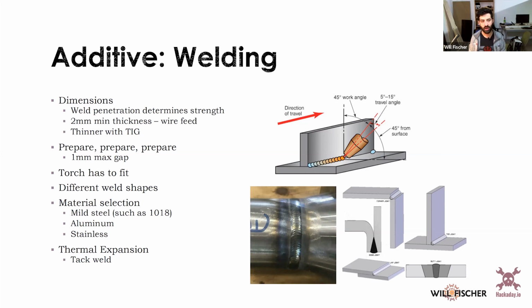Weld penetration is an important part of your structural capacity. If you have two pieces of 6 millimeter thick steel, and you're trying to join them together, but your weld only goes 2 millimeters in, your part will always fail at the weakest point. So you're going to fail along that weld because you didn't get your weld penetration deep enough. Most conventional wire feed welders are going to have a lot of trouble welding any thinner material than 2 millimeters. It's just going to burn and melt away.